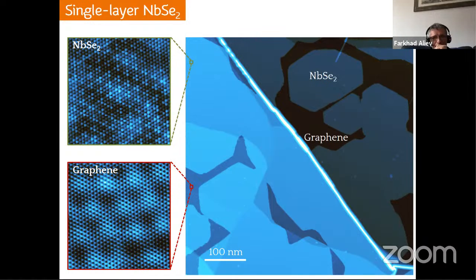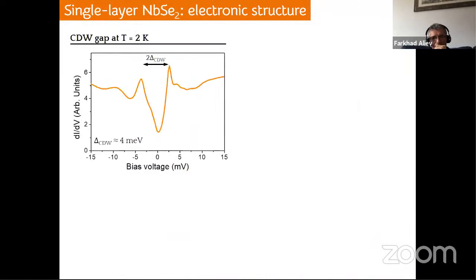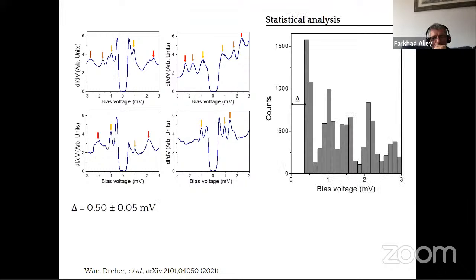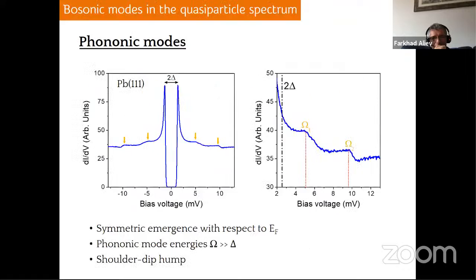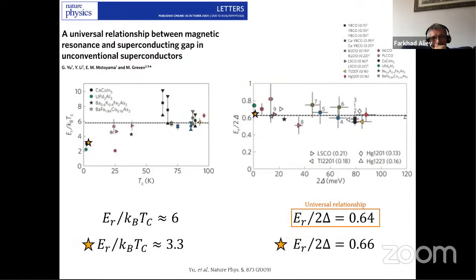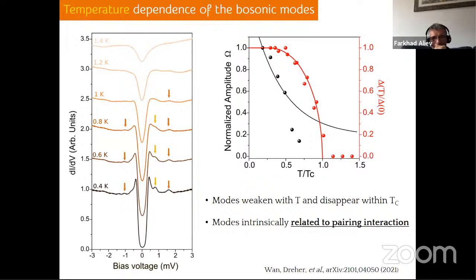And if you moved above TC, there was a black data, black points, where the extrapolation, so there were red points and black points, amplitude as a function of temperature, where for black, you extrapolated that the resonances persist above TC, and for red, they just disappeared. So what is the meaning of this? No. The red points basically is the gap size. Yes. Normalized to the gap at 0 Kelvin, and the black points is the amplitude. The amplitude of this particular one. Just wanted to show you that it decays faster than the thermal broadening.